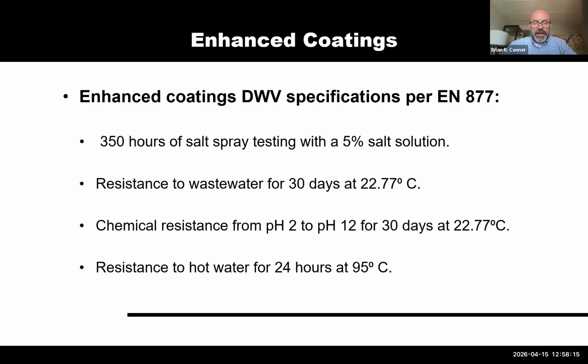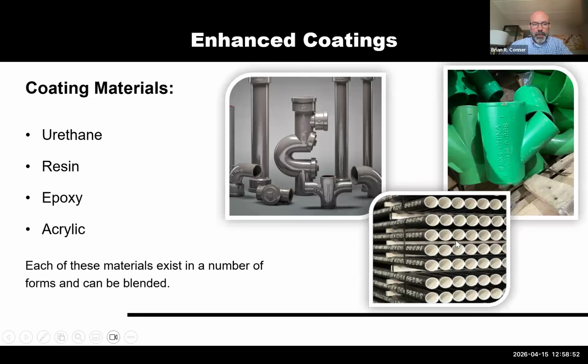And what we have done at Charlotte Pipe is taken the requirements of EN 877 and incorporated it into the listing for our products, and we've doubled the test. So where EN 877 requires 350 hours salt spray, we test to 700. Where it's checking for resistance to wastewater at elevated temperatures for 30 days, we go double that. We've checked the chemical resistance all the way down from 1 to 13. So everything that EN 877 requires, we exceeded that with the testing of our Edge HP coating.